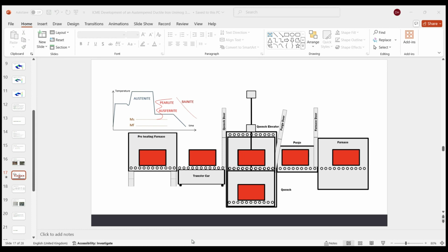They get into the back of the furnace, and this is where they heat up to around 900 degrees centigrade, so red heat. We do that in a carbon-rich atmosphere, which prevents any of the castings from scaling up in the high heat. Once they've soaked in there for the set time, and we have a casting here which is 80 millimeters thick, so it will be in the furnace for about 180 minutes. The rule of thumb is 60 minutes for 25 millimeters, so an hour per 25 millimeters. Once we've had the right soak, we come back out.